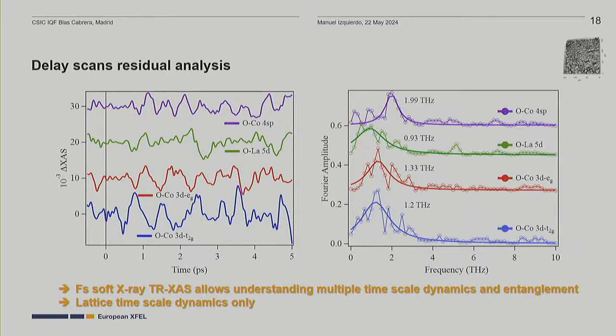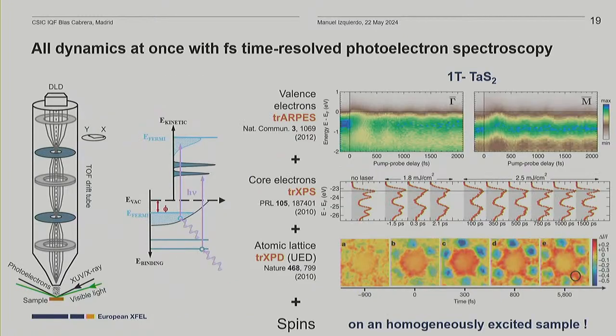The problem is that for the lattice, only the dynamics is available. So if you want to go further, are there other possibilities? Well, one very appealing possibility is to do a femtosecond time resolved photoelectron spectroscopy, because in principle you can access the valence band electrons and understand the electronic properties and also the spin properties if your spectrometer is spin resolved. You can look into core electrons, and then you can analyze the chemistry of the system, but you can also understand electron-electron correlations and many other effects in your material.